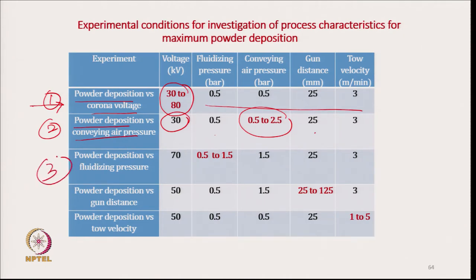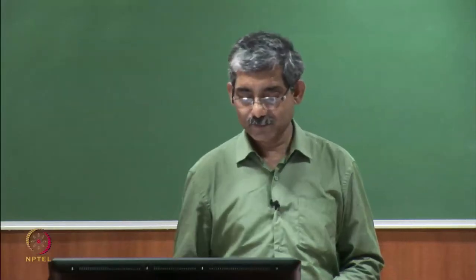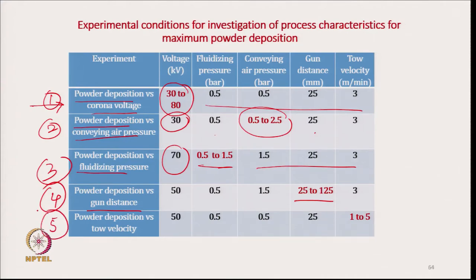In the third experiment, we changed the fluidizing pressure from 0.5 to 1.5 bar with the voltage at 70 kilovolt, and other parameters were kept constant. Similarly, in the fourth experiment, gun distance from the tow was changed from 25 to 125 millimeter. And in the fifth experiment, tow velocity was changed from 1 meter per minute to 5 meter per minute, keeping all other parameters the same, where voltage was kept at 50 kilovolt. This was the experimental setup.